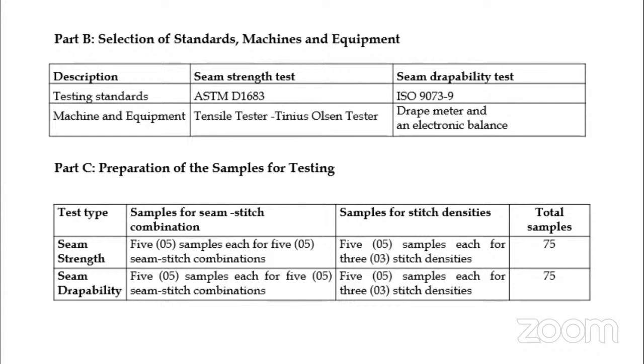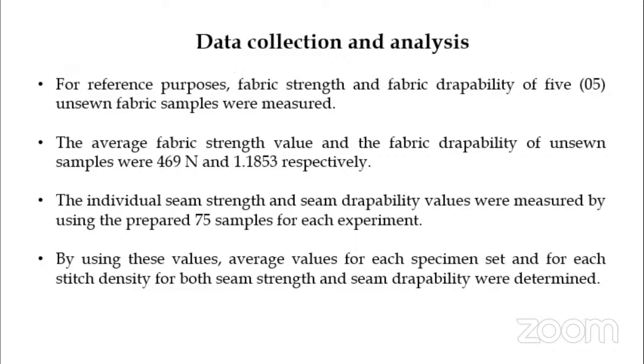Part C, preparation of the samples for testing. For seam strength, 5 samples each for 5 seam stitch combinations, 5 samples each for 3 stitch densities, so the total sample is 75. It is the same for seam drapability test. Data collection and analysis. For reference purposes, fabric strength and fabric drapability of 5 unsewn fabric samples were measured. The average fabric strength value and fabric drapability of unsewn samples were 469 Newton and 1.1853 respectively. The individual seam strength and seam drapability values were measured by using the prepared 75 samples for each experiment. By using these values, average values for each specimen set and for each stitch density for both seam strength and seam drapability were determined.